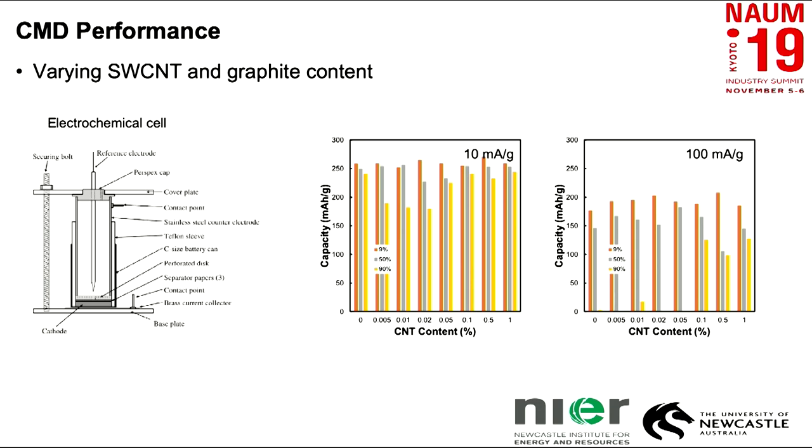In the middle graph that you see there, the performance, with high levels of conductor present in the electrode, we do utilize the full amount of active material present in the system. When we start to go into high rates, when we have less and less graphite being included into the electrode, this is where the carbon nanotubes actually really improve their performance. You can see on the right-hand side over there, when we have 0.1 up to 1% of carbon nanotubes included